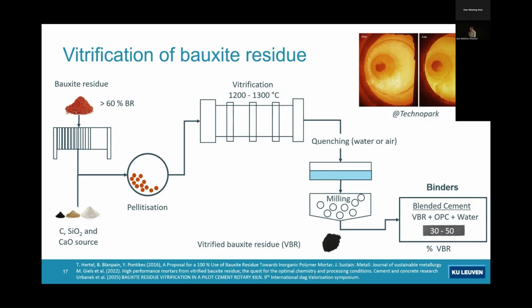So I've done this in pilot trials. We have even made it at Technopark with Jan Urbanek, really making this material in a rotary kiln, which was an interesting experiment. It was able to produce an iron-reduced melt in a rotary kiln. It has quite some challenges, still not optimal, far from it, but it was possible. So this was possible, but the question for you is, how did we use FactSage?